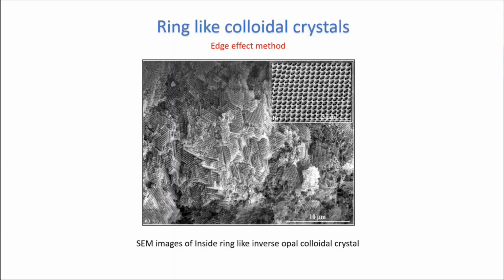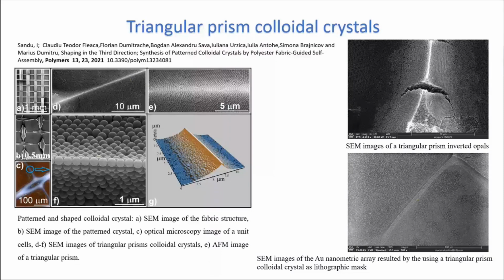And the second attempt, we obtained by using polymer nets to order the silica and polystyrene nanometric spheres in triangular prisms, very well ordered triangular prisms. But this triangular prism forms a unit of a much larger pattern, a net which can have billions of these units. And after that, even each unit can be modified, becoming more complex. This system could be transformed into an inverted opal superstructure, a super net.